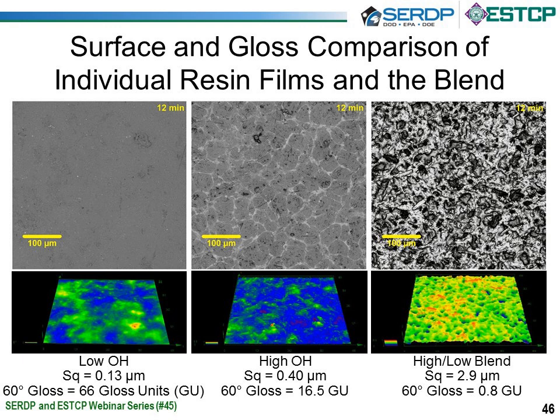Finally, on the right side, you can see the blend of the two, 1-to-1, low OH and high OH cross-linked. You can see that the surface roughness significantly increases to 2.9 micron, and the gloss units is down to less than 1, which is highly desirable for a low gloss military coating. So clearly there's a synergistic effect of the addition of the pigments with the polymer phase separation, and that's how we've been able to characterize this, where the flattening agents, the fillers alone, were not able to achieve that.